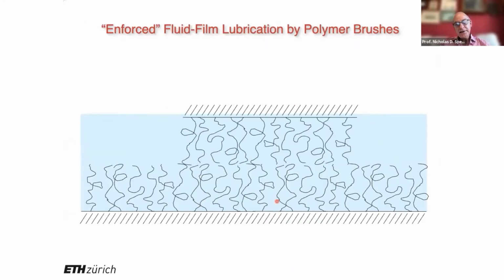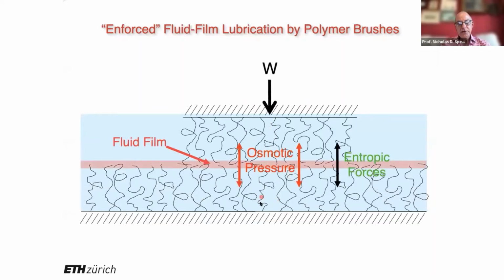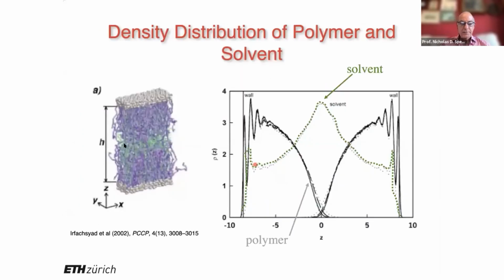And what's going on here, and this is stuff that came out of Jacob Klein's group a long time ago, is that we have two sets of brushes with some forces acting. We have an osmotic pressure that inhibits the compression of the brushes, and we have entropic forces that inhibit the overlap of these brushes. And we have a fluid film at the interface that isn't obvious here, but modeling and neutron experiments have shown that the distribution of monomer going out from the surface to the interface falls off parabolically. So you have a maximum in the solvent concentration in the middle, and that's where you get the lubricious layer. That is the lubricious layer that gives you the low friction.